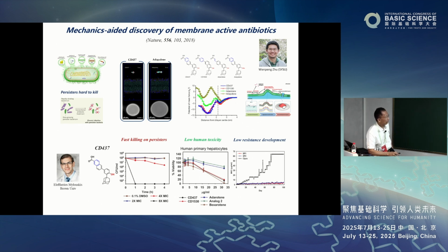It turns out we were able to identify a couple of good candidates. For example, this is the free energy when a molecule invades the bacterial membrane. You can see that, for example, this blue one and the red one have an energy sink inside the membrane. This is a good candidate for an antibiotic. For others, the energy increases when they invade the bacterial membrane. That means this particle will not be able to penetrate into the bacterial membrane.